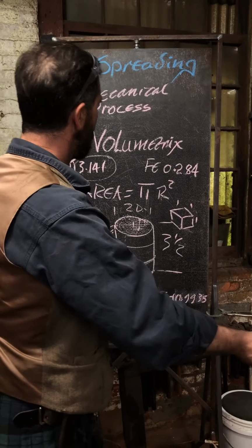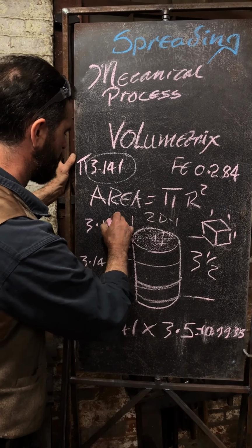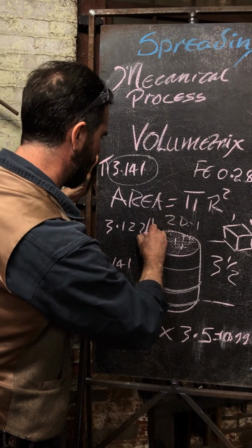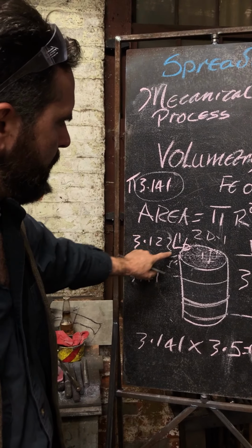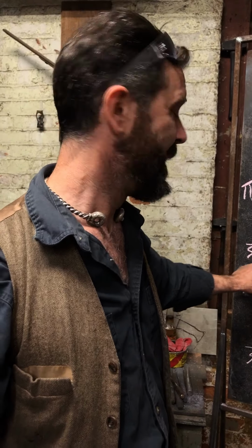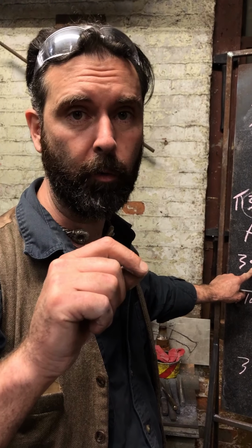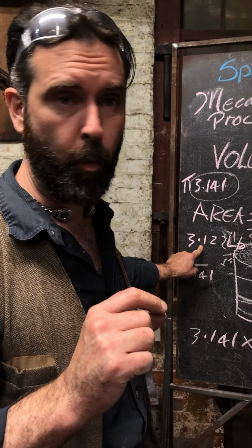So the weight of this was 3.122 lb. The reason that I add this little extra portion here is you're going to get material loss from scale through forging. You're also going to lose a little bit through punching the hole. I usually find that I lose about 1/2 ounce in the slug when punching.